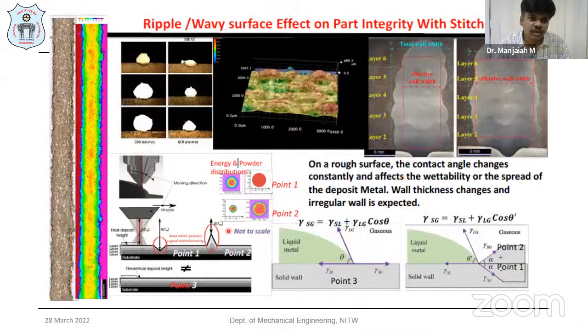And if you are not properly optimizing the process window, this kind of ripple and wavy surface is going to occur in the part geometry with the stitched n number of layers. You can see this is the 3D profile. How each layer's wetting angle is going to directly affect the solid wall. On this rough surface, the contact angle changes constantly from layer to layer, which affects the wettability or the spread of the deposited metal.